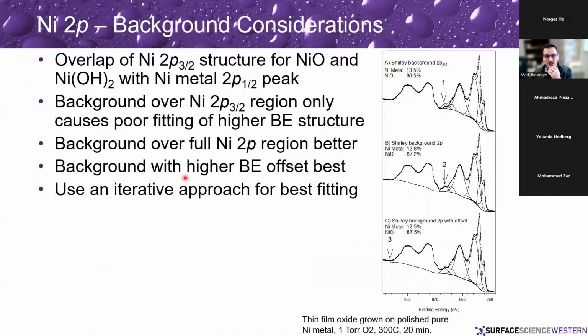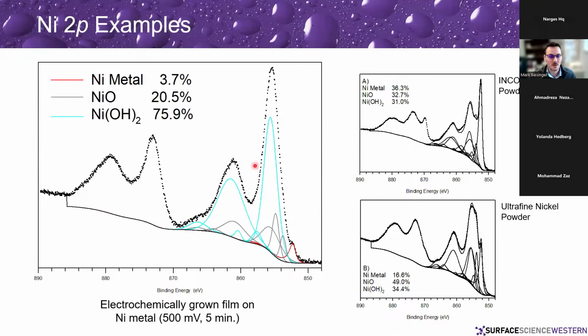Sometimes you have to play around with backgrounds. For example, the Shirley background doesn't necessarily work perfectly for some of these systems because it's based on how much photoelectron yield is coming out. And so sometimes you have to do some things with offsets to force the fitting using an iterative approach. That's something you can get into by looking at some of the papers that we've written on this. But anyway, as you go through this curve fitting process with unknown samples, you can very easily and very accurately pull out how much of the different species you have. So how much nickel metal, nickel oxide, nickel hydroxide.